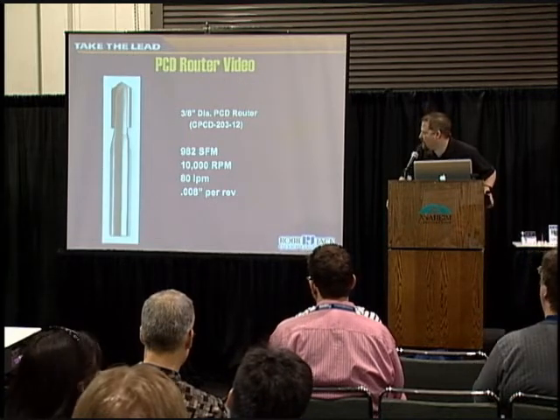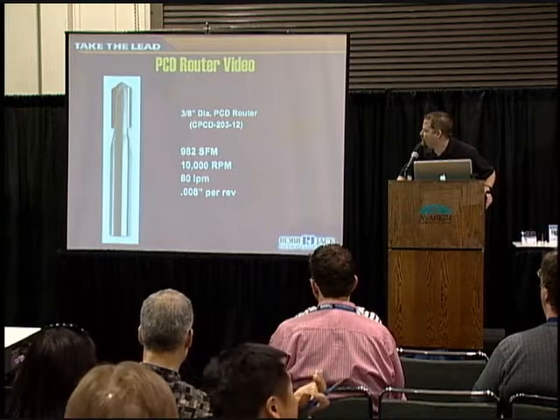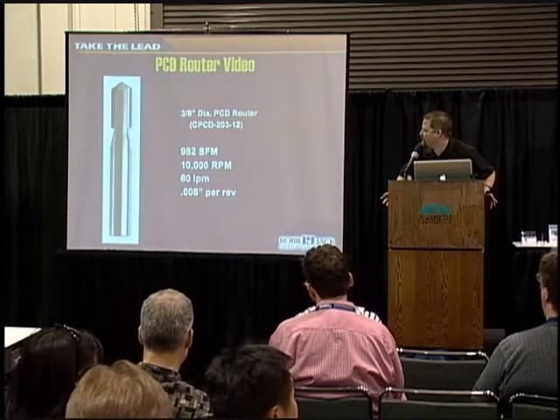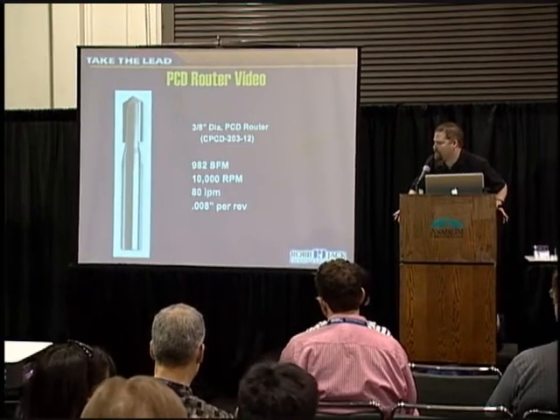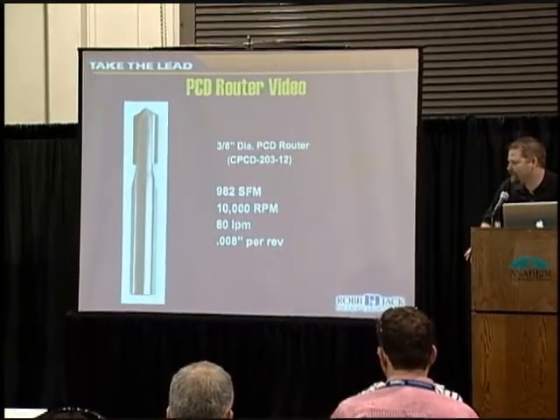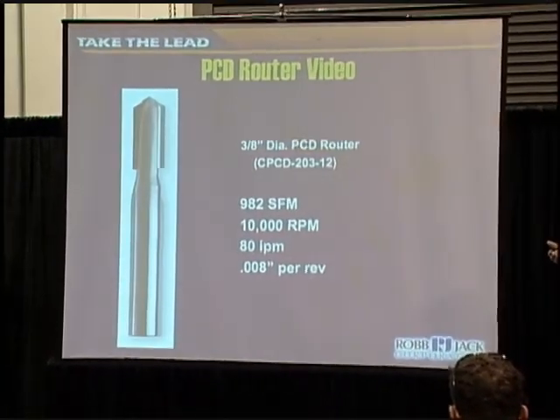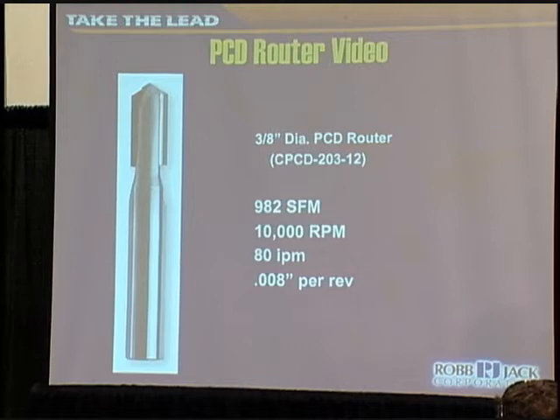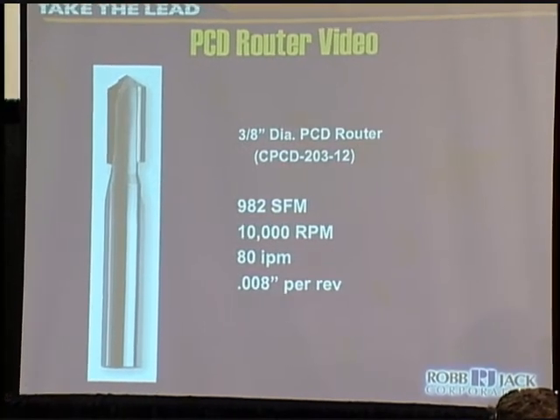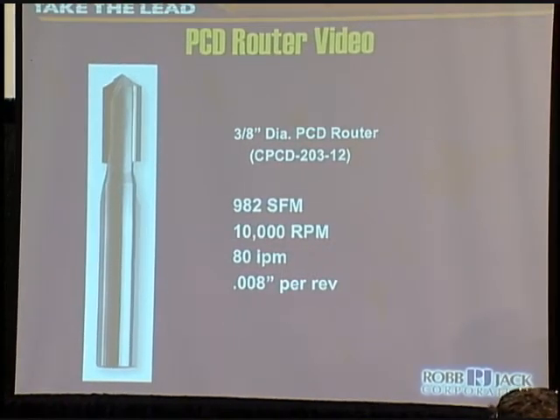So the video that we're going to show, the tool's running 10,000 RPM and 80 inches per minute. Typically, most people try to run their trimming tools too high of an RPM and too slow of a feed rate, and the problem is you generate too much heat. By running at a more conservative RPM but a faster feed rate, we're able to get a lot more tool life out of the part.